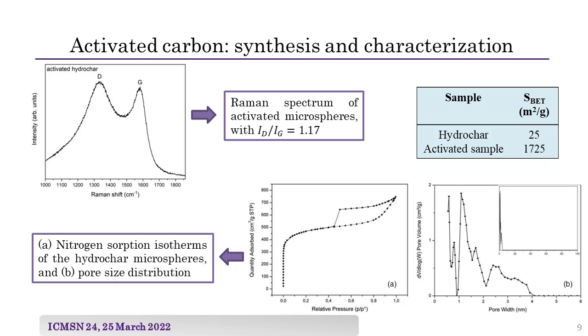a graphitization degree higher with respect to the starting microspheres. The specific surface area calculated from a nitrogen adsorption-desorption experiment is 1725 square meters per gram, which is not in the higher range of the specific surface areas observed in activated hydrochars, but is noticeably higher with respect to the hydrochars obtained by the hydrothermal carbonization of orange peel.